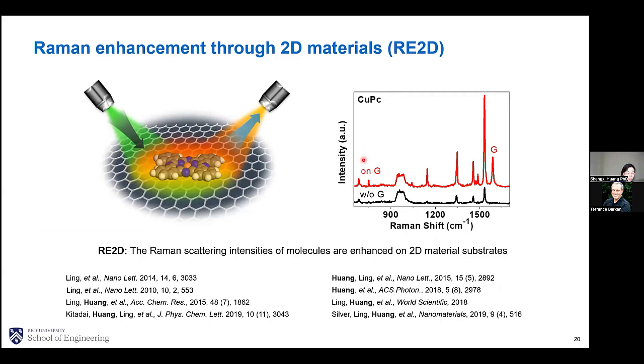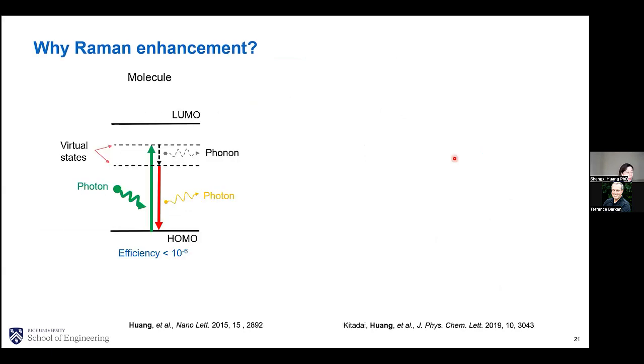You can see when we put this molecule on graphene substrate, several signature Raman modes of this molecule are enhanced. So why do we have such an effect? Well, if we just look at the Raman process for the molecule itself, the molecule has HOMO and LUMO levels. And if we measure Raman spectra, we shine photons into this molecule.